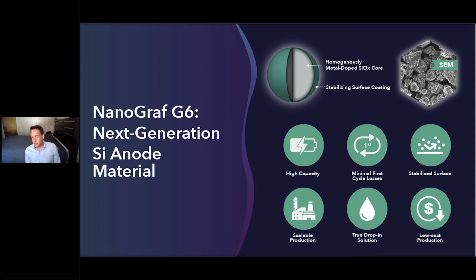So again, just as a recap of the materials, what we've been able to do is retain the high capacity of silicon oxide through this doping process, reduce first cycle losses, so first cycle efficiency of around 90%. And again, we've developed a number of special proprietary coatings that improve the processability of the material and the cycle life of the material. And again, we've already scaled this material up to 10 tons with our partner in Japan, JNC. And obviously we'll be further scaling that this year as well.